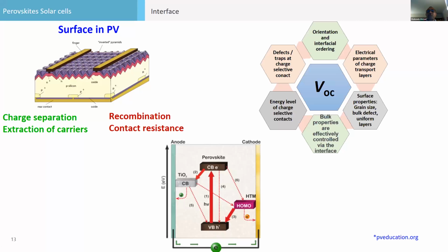The current we can modulate by designing a new absorber or by compositional engineering. The VOC, the open circuit voltage, which is also very important, we can improve by defect passivation. This has also been done in silicon. Now we are doing it, and the community has seen a very good jump in efficiency. We passivate the defects and the grain boundaries. We can also change the orientation and interfacial ordering, which is another thing we are working heavily on, in layered perovskite.